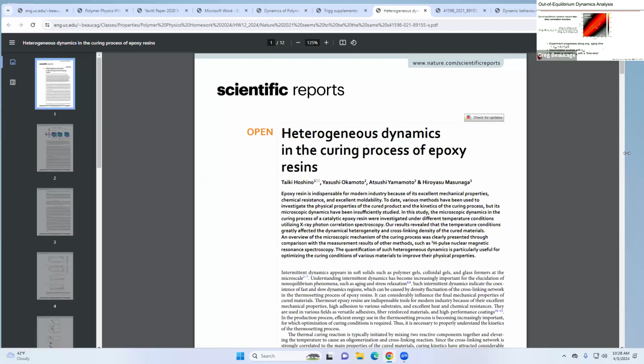Essentially, what I want you to look at is this diagonal here. If we go along that diagonal, that's the average aging time of our experiment, where we start our experiment here and end it down at the end. So if I track along that, that's basically the progression of the curing process. If everything on both sides of that diagonal is symmetrical, that means our timescales are not changing in our experiment. It's at equilibrium. So in the pre-cure state, we were really happy to see that things are moving around but not changing on the timescale of our experiment. There's one relaxation time that defines this material system, and we calculate that by doing the autocorrelation function.